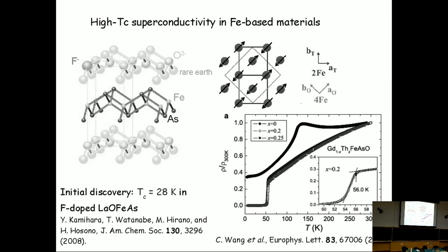And that's interesting because the structure itself is tetragonal at high temperatures, while at low temperatures we have a distortion in the lattice. So here you see in blue the tetragonal unit cell in the AB plane, and at low temperatures you have an orthorhombic distortion, and so you have this green rectangular lattice, which defines an orthorhombic structure with 4 iron per unit cell at low temperatures, while the tetragonal structure has 2 iron, half the volume, per unit cell.